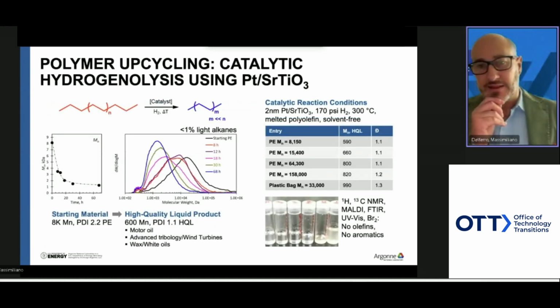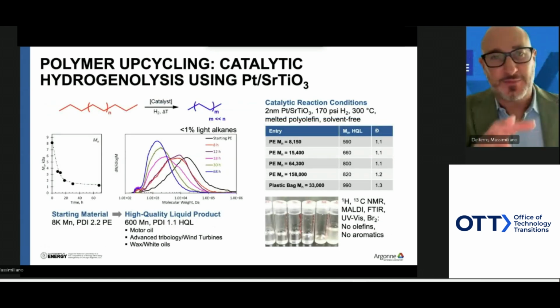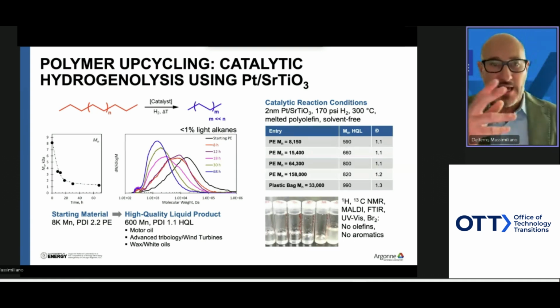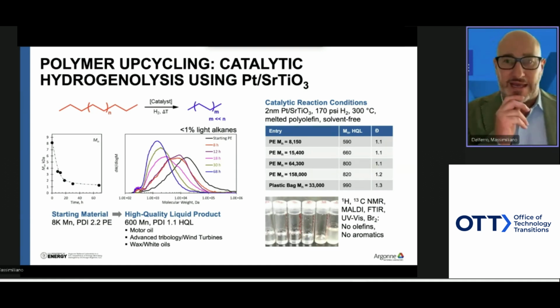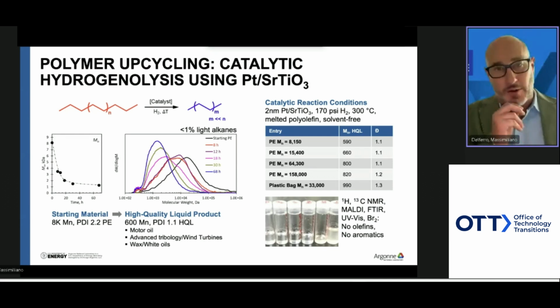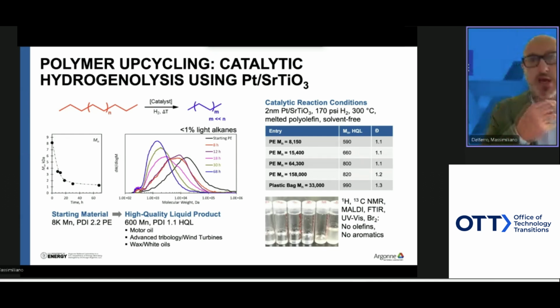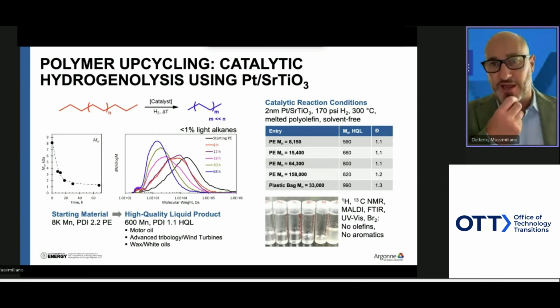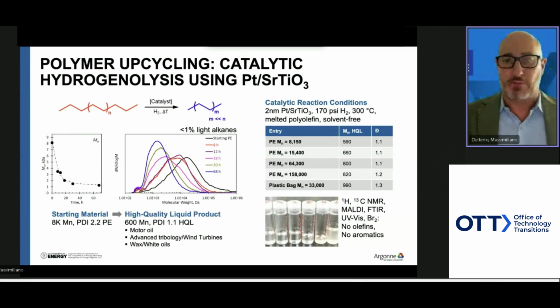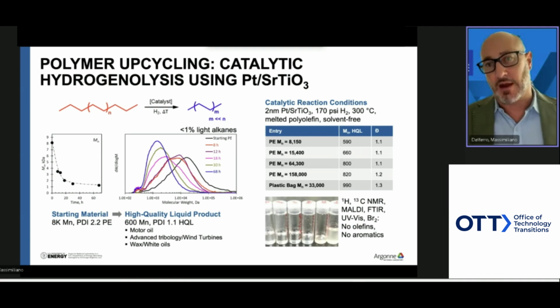Let's deep dive a little bit into the chemistry. I hope that I'm not going into too much detail, but the idea, as I mentioned before, is we want to cleave carbon-carbon bonds with hydrogen in the presence of a catalyst at high pressure and high temperature. The temperature is roughly 300 degrees. There is no solvent. It's a solvent-free reaction. And as you can see from this graph, we are able to cleave in a very selective way the long polyolefin chain to a narrowly distributed liquid that we call HQL, high quality liquids.